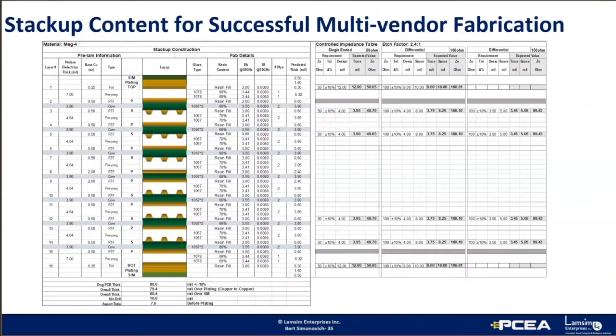And of course, the line width and space geometries, as well as calculated impedance, is normal for fabrication notes. But what is often not captured is the etch factor of the trace and frequency used for Dk/Df for the impedance calculations.